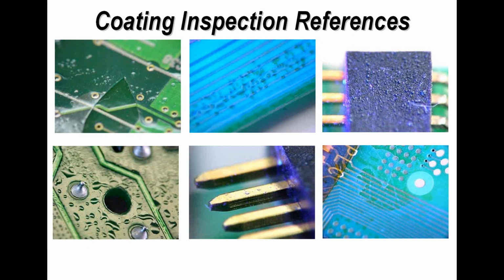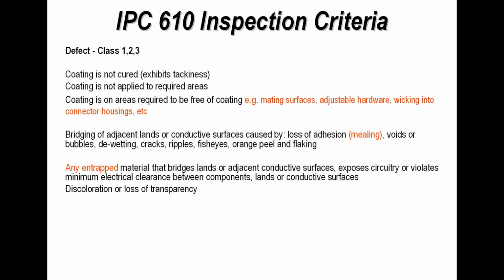And again, just illustrated, what's happened here is capillary action has allowed the material to penetrate through the body of the connector onto the pins, which would obviously affect the contact resistance. And finally, on the right bottom view, I show coating not adhering to the surface because of contamination, which was on the board assembly prior to the coating operation. So again, it depends on controls of those.